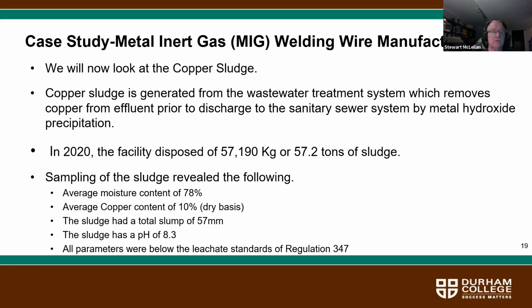So sampling of the sludge revealed the following. This sampling was all done in 2020. The average moisture content was 78%. Average copper content was 10% on a dry basis. The sludge had a total slump of 57 millimeters. The sludge has a pH of 8.3. The sludge was tested through TCLP testing, and all contaminants were below the leachate standards of Regulation 347.